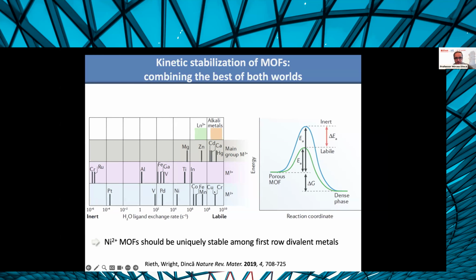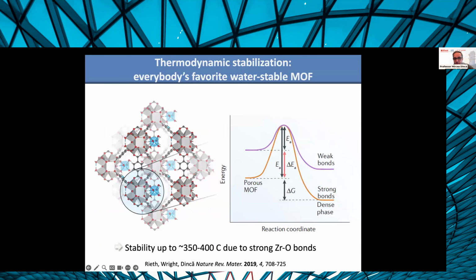So that means that if one copper-based MOF is stable for 1 second or 1 day, the nickel version of the same exact MOF will be stable for 1,000,000 days. And that is sufficiently stable for all of our lifetimes combined. And so really choosing the right metal for making a stable MOF is going to be very important. Even zirconium MOFs that are touted to be very, very water stable, I would argue are still kinetically stable, because the zirconium oxygen bond simply means that, as far as comparing it to, say, a zinc oxygen bond, both the dense phase and the porous phase are lower in energy, which automatically makes a kinetic barrier higher.